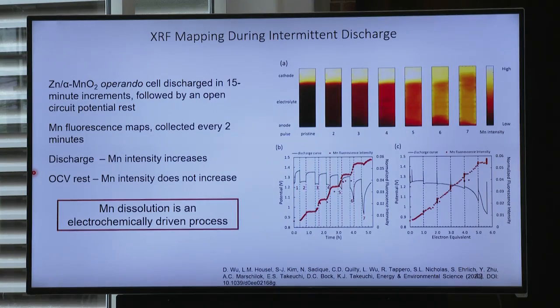So the next set of experiments was mapping the cell, but in an intermittent electrochemical process. So what we're doing is we're discharging the cell, then we pause. Then we're discharging the cell, then we pause, and then we keep going. So think of it as applying pulse, wait, pulse, wait, pulse, wait. And we saw something pretty incredible. If you look at the maps on the top, that bright white-yellow spot is the cathode. But as we continued with the discharge, what we saw is more and more manganese going into the electrolyte layer. So this meant that the manganese was in fact dissolving into the electrolyte, and that was part of the electrochemical process.